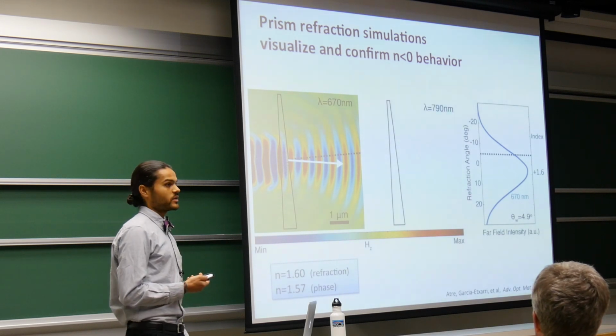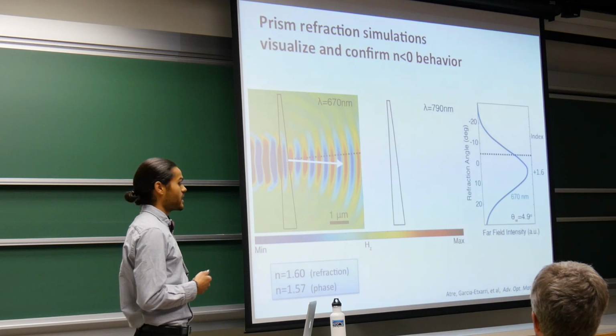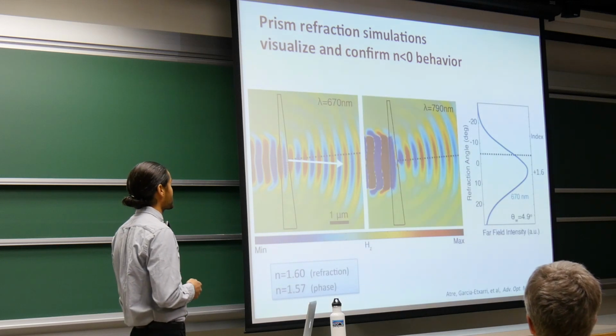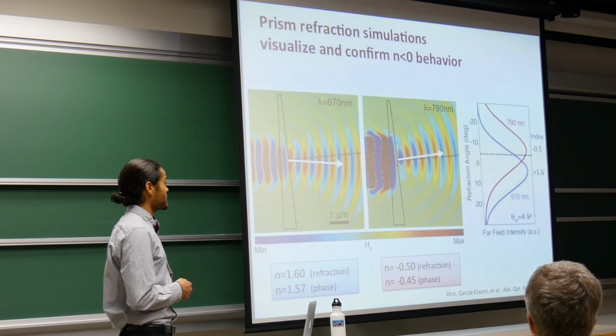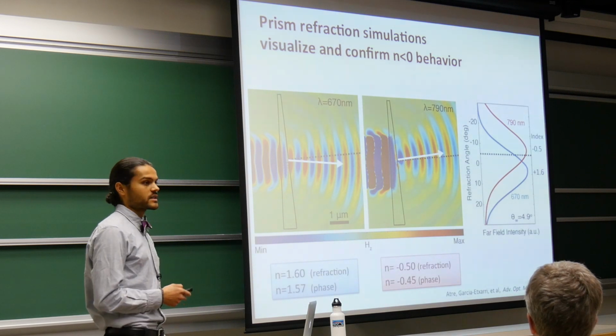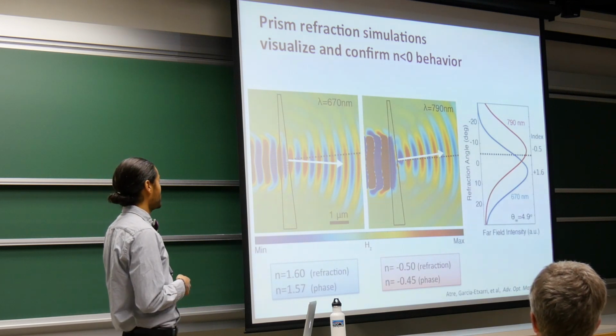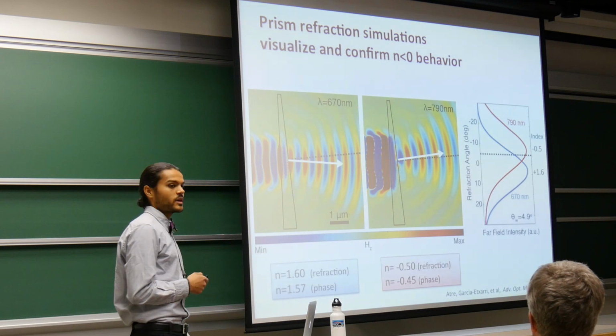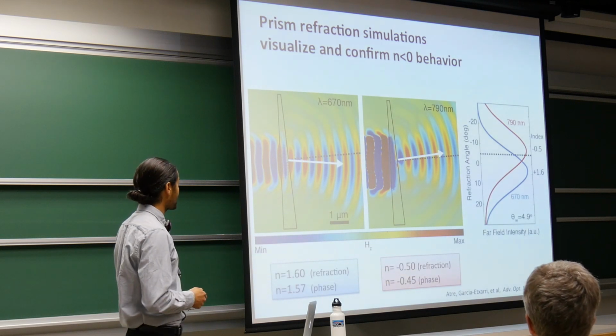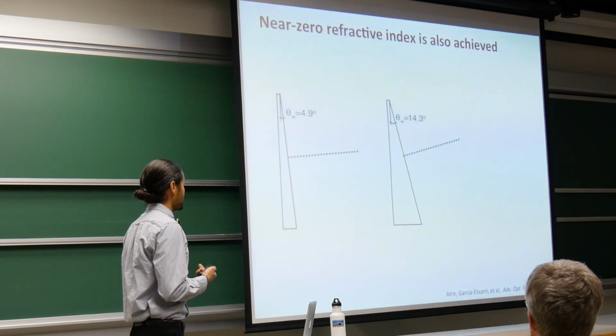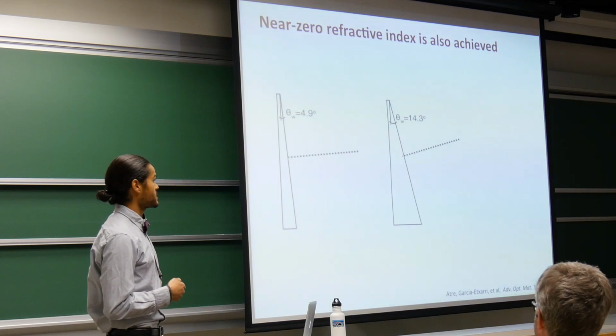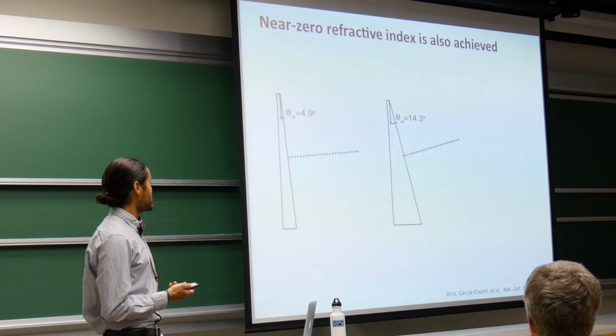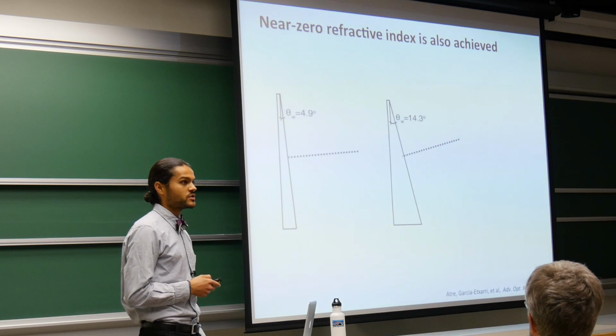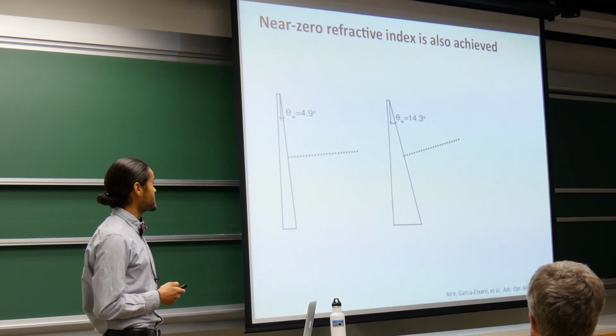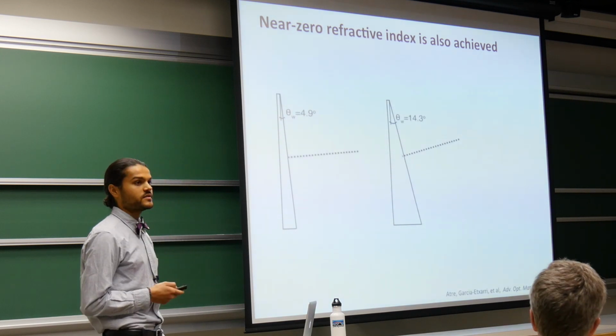Now at a wavelength where we expect the light to bend in the other direction or have a negative index of refraction, we do in fact see that that is the case. And again, the index calculated via this visual method corresponds quite well with the phase-based technique. To make sure that this effective index that we've calculated is not particular to the geometry of the system that we're looking at, we also look at wedges of different angles.